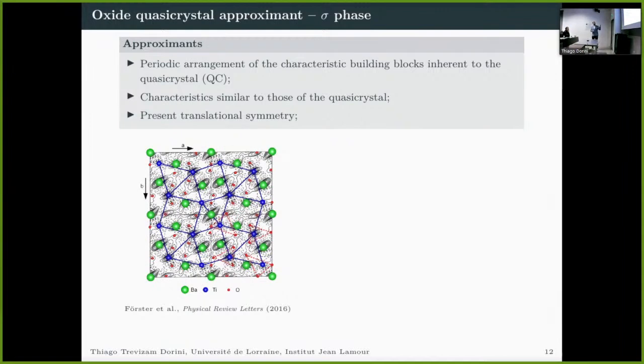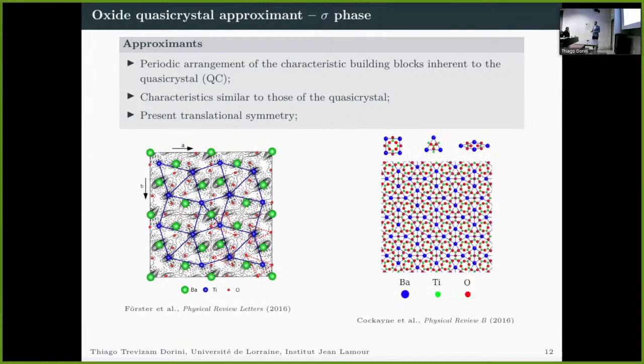And here I'd like to highlight the first discovered approximate phase for these systems, which is the sigma phase. Förster and his collaborators determined the first model for the structure by using synchrotron X-ray diffraction. And this is the initial structure. It's interesting to highlight that in this model, they consider that what we see on the STM images corresponds to the tilings of the titanium atoms, these squares and equilateral triangles. In addition, there's a second alternative model for these phases, which was derived by the work of Cockayne, which will have these tiling configurations. And in this case, what we see on the STM images are the electronic density of the barium atoms.